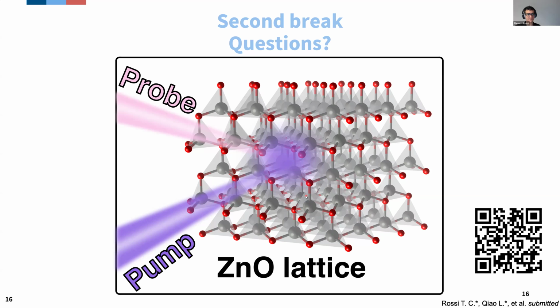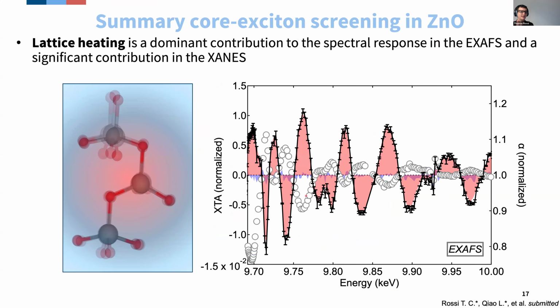Yeah. So then what comes is essentially a summary of what we have found on zinc oxide. I will only briefly describe what more we found out on this system, not to go too much into the detail. But the take-home message first is that, remember from where we started and where we ended, lattice heating is extremely important for these picosecond experiments. It should be dealt with to be able to interpret experimental data.